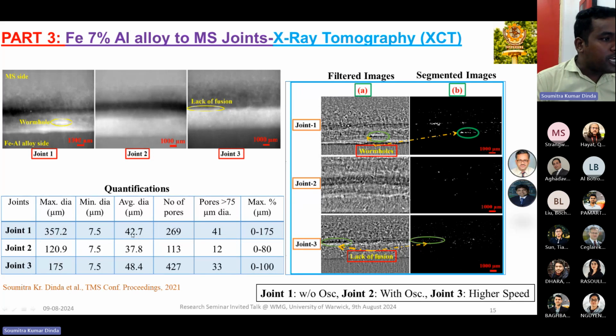We are not talking about the individual parameters, like 7.5 or 267 or 269. But we can get a trend from joint 1 to joint 2, using the oscillating beam. We can see that the numbers are decreasing, and the big sizes are decreasing. We are not asking about the individual numbers. But from joint 1 to joint 3, we can see the numbers are increasing, but the maximum pore size is decreasing. So we can get a trend before going to the 3D tomography result. We know that joint 2, using the oscillating beam, gives a slightly superior result, a superior property in terms of defects.